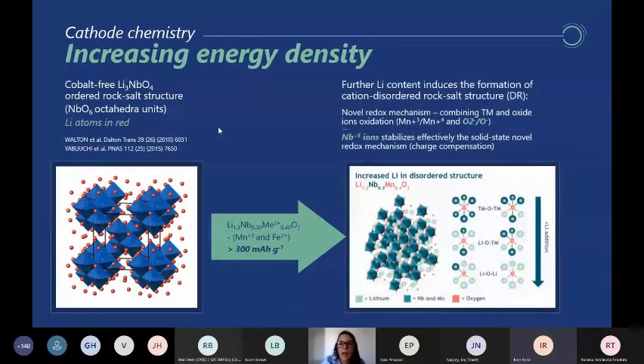So for cathodes, in the first case, niobium has been used to develop materials with high energy density and enhanced stability with low content of cobalt or even cobalt-free materials. In the first case, we have a cobalt-free lithium transition metal oxide that has been explored from the understanding that more than 10% of lithium excess in the structure creates an oxygen transition metal channel percolating network and induces the formation of the cation disordered rock salt structure.